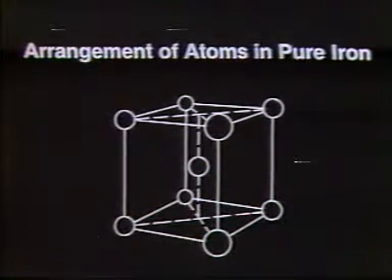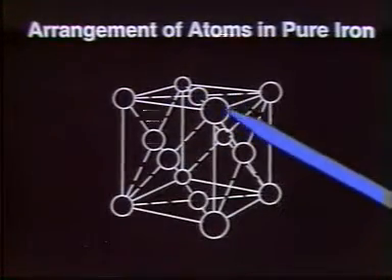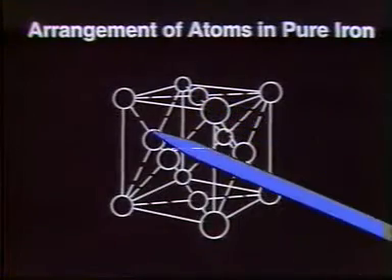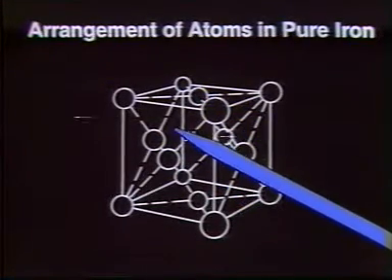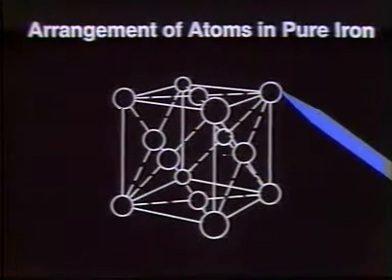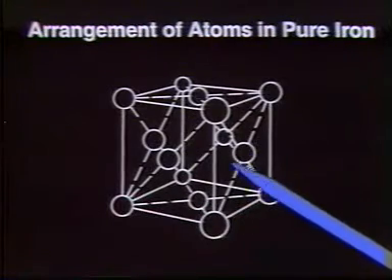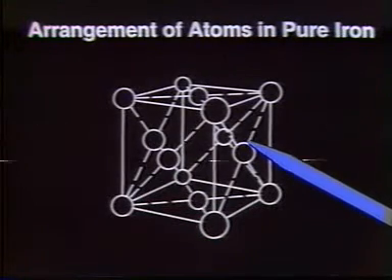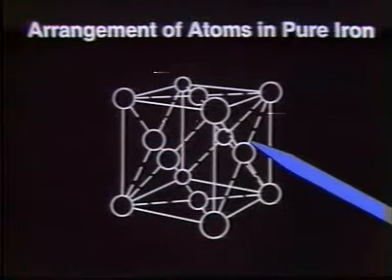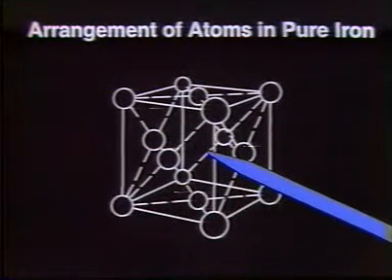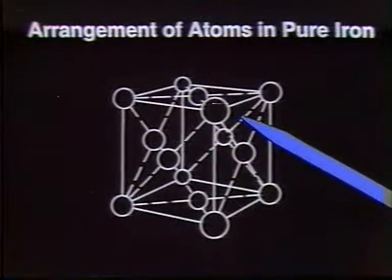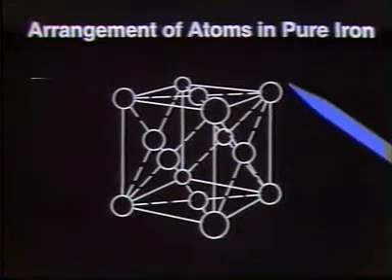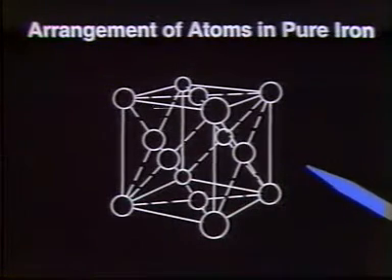If you look at the face-centered cubic structure, or the structure that's going to exist at a higher temperature, we see a structure that looks like the next one, a face-centered cubic structure now having an atom at every corner, an atom at every face. There's 6 faces, and so we have 6 face atoms. The corner atoms are still going to contribute 1/8 of an atom per unit cell, but the face atoms are shared by this unit cell and the unit cell immediately adjacent to it, so it contributes 1/2. And since there are 6 faces, that means we have 3 atoms contributed as face atoms to the unit cell, or we have a total of 4 atoms per unit cell in this particular structure and only 2 atoms per unit cell in the body-centered cubic structure. So you see where if the lattice parameters stay the same, although it doesn't stay exactly the same in that transformation, we would expect to get a rather big volume change.